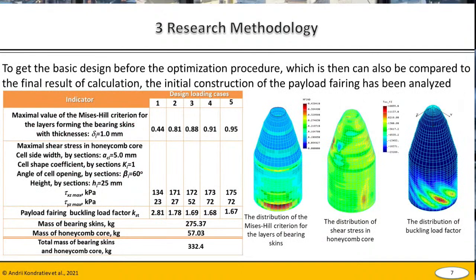Before the optimization, it was reasonable to analyze the basic design of the payload fairing, and in this slide you can see the results. The Mises-Hill criterion for the layers of bearing skins, shear stresses in the honeycomb core, buckling load factors, mass of both the bearing skins and the honeycomb core, and the total mass of sandwich structures.